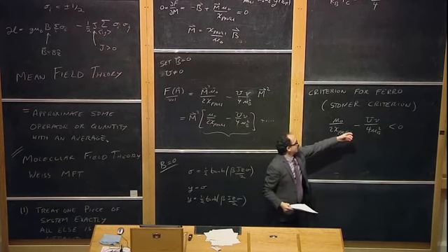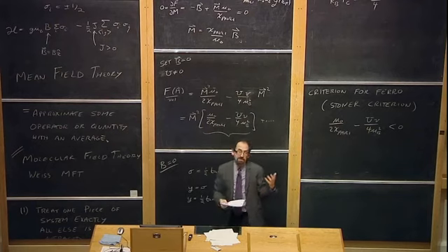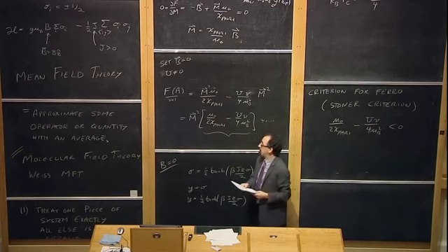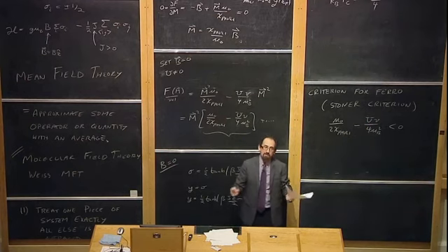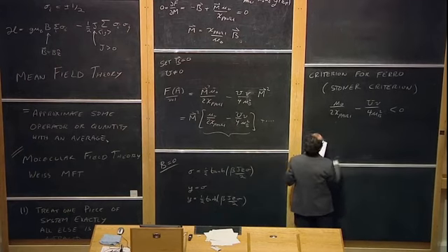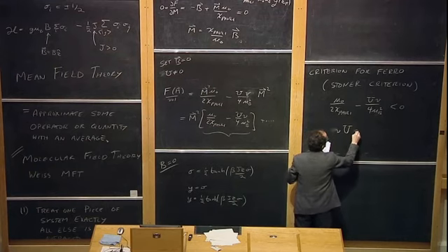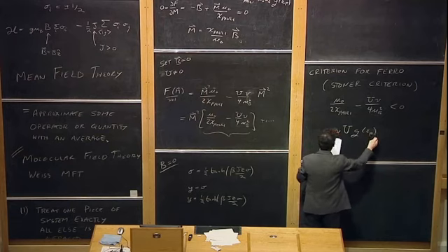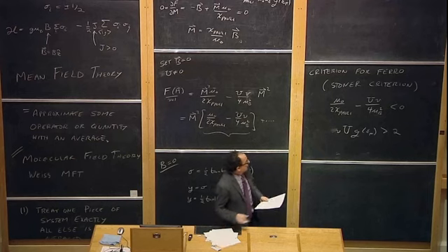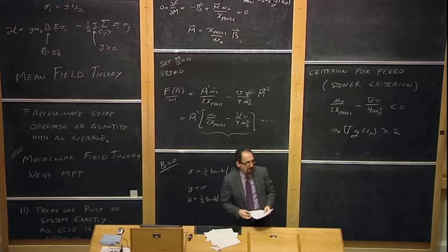So when you turn on the interaction strength strong enough, then the interaction strength wins, and it wants to have the spins polarized. Whereas if the interaction is not strong enough, then in fact it's more beneficial to have an equal number of spin ups and spin downs because you save kinetic energy that way. Actually, putting in the definition of chi Pauli, we can write this as volume of the unit cell times U times g at EF should be greater than 2. It's equivalent.